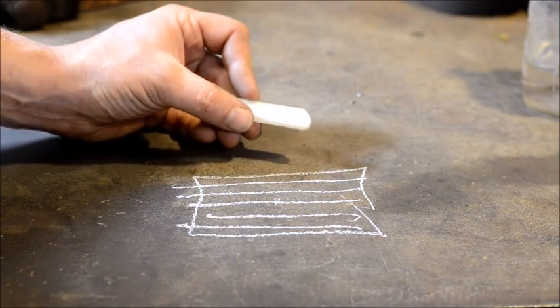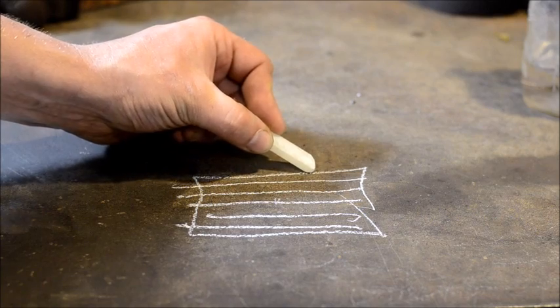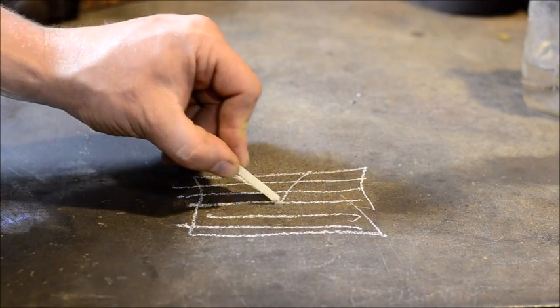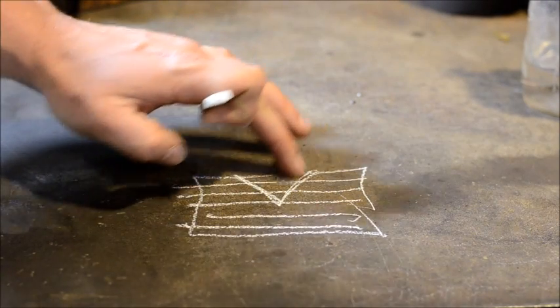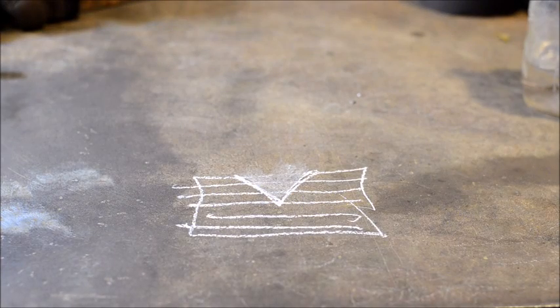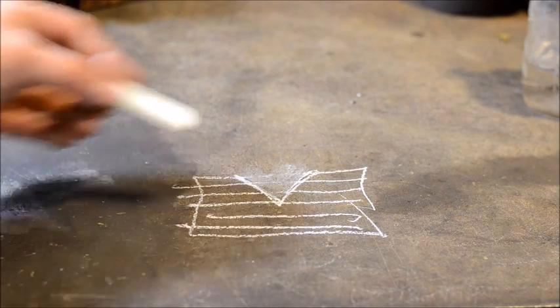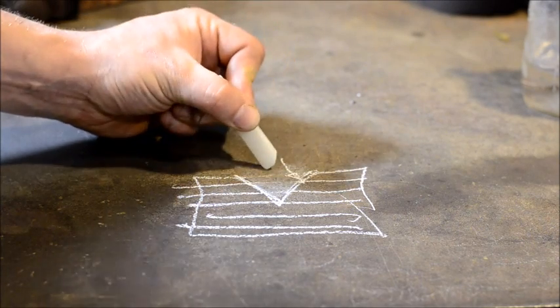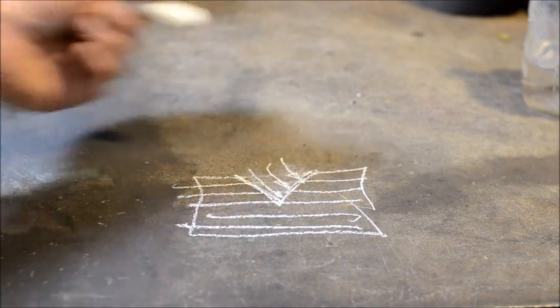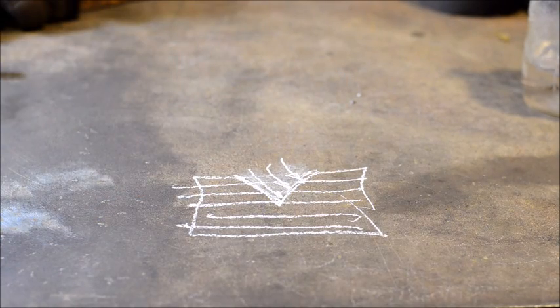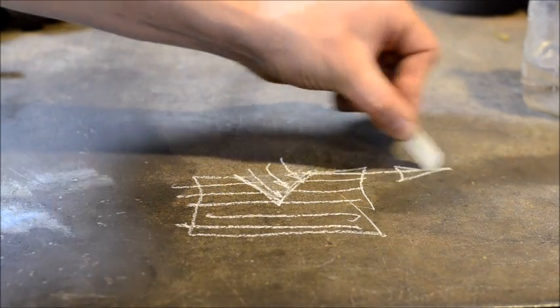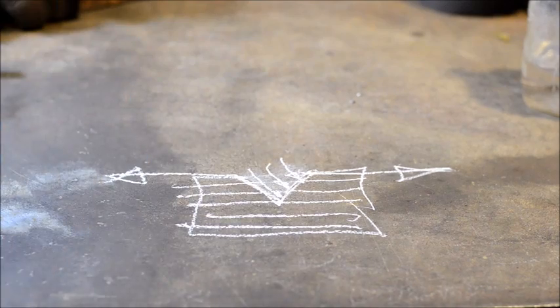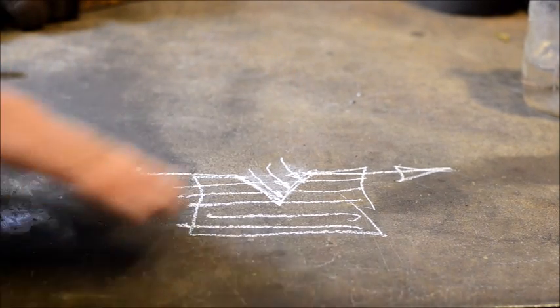What I'm going to do is I'm going to actually take a countersink bit, and I'm going to drill part of the way down into my billet as it sits, and remove that material. And what that's going to do and create for us is this little notch, but what it's really doing is it's exposing these layers of the copper and nickel. It's exposing those layers. And what I mean by that is we're going to bring these up to the surface by hammering that out that direction and this out this direction. And what that's going to do is that's going to give us a pretty interesting pattern.